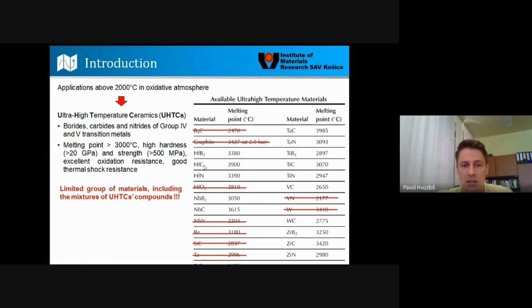Those are basically the borides, carbides, and nitrides of group 4 and group 5 transition metals, because those are the materials which have the highest melting temperature of the materials known. These carbides, borides, nitrides have not only high melting temperature, which makes it possible to apply them as an ultra high temperature material, but they also have high hardness and high strength. At the same time, they have excellent oxidation resistance and good thermal shock resistance, which is necessary during, for example, re-entry of space vehicles to Earth, because they need to somehow take away the heat from those edges.